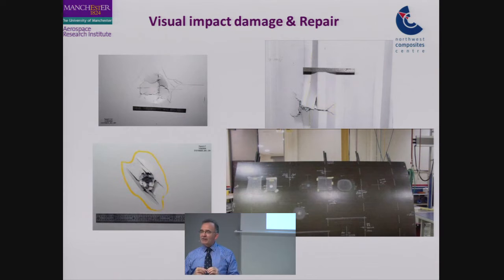So if you have damage in the primary structure, you have to drill holes, and your patch has to be riveted. But what is the problem with rivets? What is the problem we have with rivets? We have to drill the composite. By drilling, we cut fibers, and then we go back to stress concentration factors that we have to deal with in metallic structures. And when we say composites do not fatigue, we know very well now, once we have holes and rivets, fatigue can become an issue, especially as we moved to an era where now our composite structures are becoming primary structures and are heavily loaded in comparison to composites in the late 70s, early 80s, when they were used mainly as secondary structures.